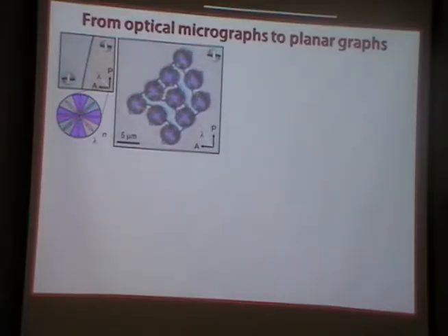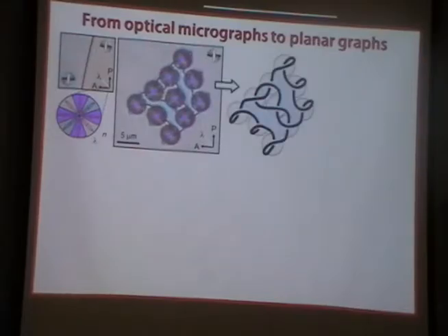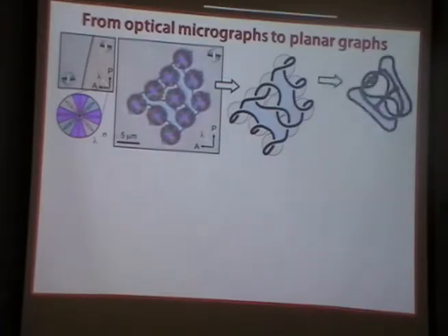So it happens always. You don't have to have a regular array of particles or something like that. Whenever you go across the disclination line, the twist of the molecules will switch from left-handed to right-handed. And just by looking at such a structure under the microscope, you can reconstruct the shape or the topology of the loop which is entangled around.